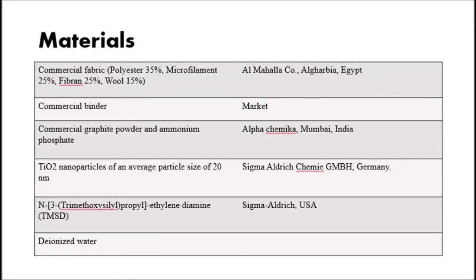The materials used are commercial fabrics with the following composition: polyester 35%, microfilament 25%, Fibran 25%, and wool 15%. Commercial binder was also used, and commercial graphite powder and ammonium phosphate, TiO2 nanoparticles of an average particle size of 20 nanometers, TMSD, and deionized water.